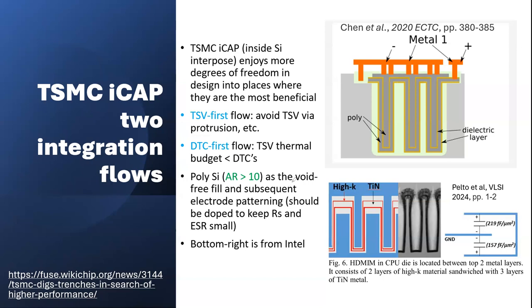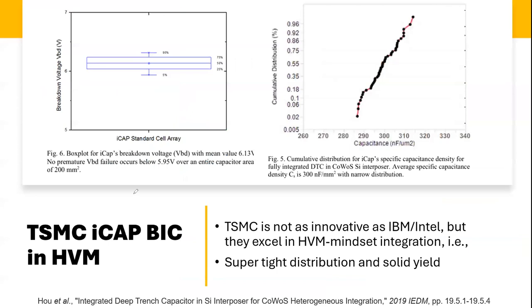But you need to do some kind of doping. You cannot use pure silicon. You need to dope it to keep your RS and ESR small. You need to keep the resistance small. You want a metal. You do have metal, but this is your electrode now. Your electrode is here, but inside you still need some electrode to keep your ESR and RS low. So I think you need to dope it. And then you see this is very nice, a straight line, no serious kink observed. Yeah, ICAP, and they have a very tight distribution.